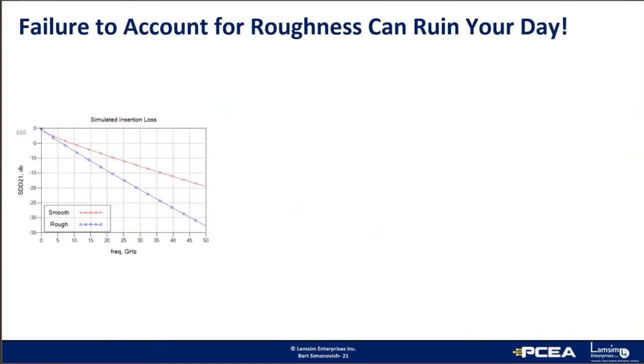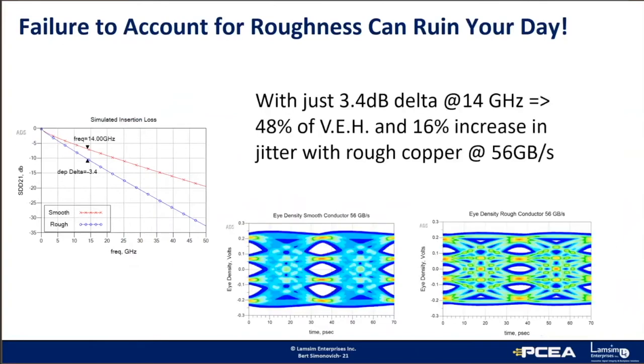Failure to account for conductor roughness can ruin your day, especially if you're trying to push 56 gig PAM4 signaling down your channel. And here we see with just 3.4 dB delta at 14 gigahertz, there's a decrease in vertical eye height of about 48% and a 16% increase in jitter with the rough copper at 56 gigabits per second.